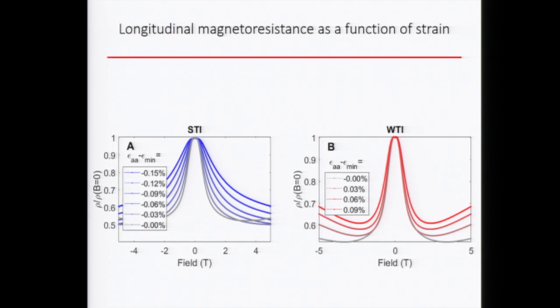Yes, go ahead. Strong and weak in this case, is there any signature in this particular longitudinal resistance data that distinguishes the transition, or is it just the effect on the negative magnetoresistance? Right, so we can independently determine that from just the zero field resistance, on either side of the minimum. But we think we probably see some signature that distinguishes between strong and weak, which is still under investigation.